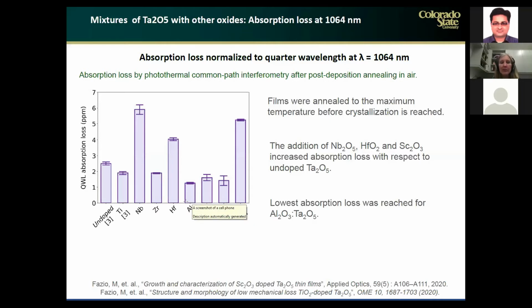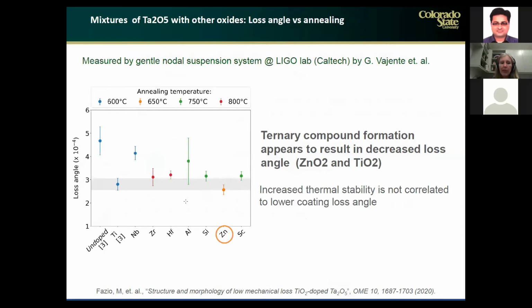So now what I am showing you here is how the loss angle varies with the different materials in the mix. And again, the values are quoted at the temperature right below the crystallization temperature. What these results show is that in most cases, the mechanical loss reduces when we mix tantala with other materials. However, with titania and with zinc, the two materials in which we form these ternary alloys, we obtain the minimum value of the loss angle, which is consistent with what has been measured before, about 2.8 x 10 to the minus 4.